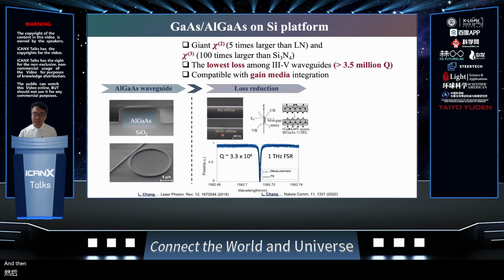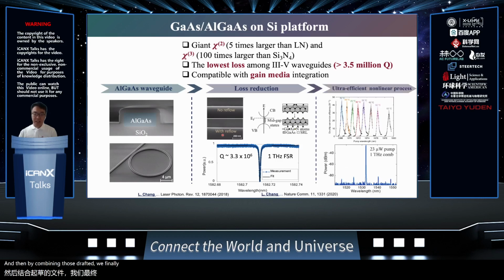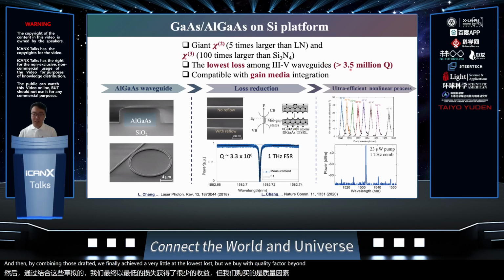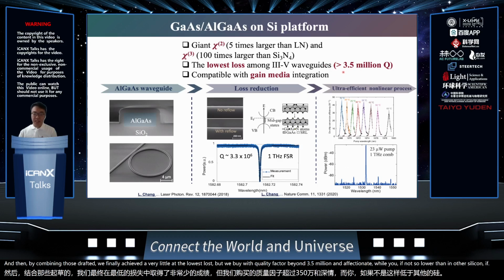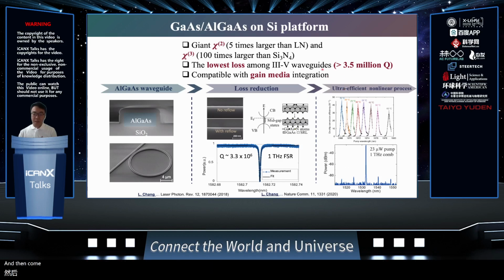By combining those strategies, we finally achieved the lowest loss III-V waveguides, with quality factor beyond 3.5 million. Such a value, if not lower than silicon, is definitely one of the best semiconductor waveguides we can get. Then combining this low loss with the giant nonlinearities this platform has, we achieved the most efficient second and third order nonlinear processes on chip. At a microwatt scale, we can get significant frequency conversion into the second harmonic wave, as well as parametric oscillation for microcomb generation.